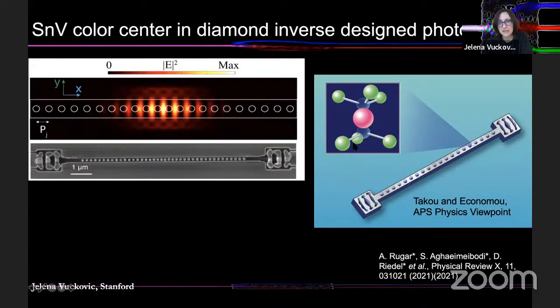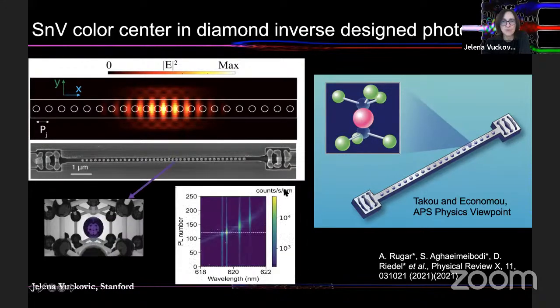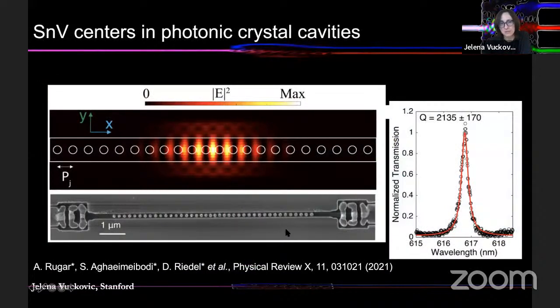Recently, we managed to do that and demonstrate a quantum photonic interface for tin vacancy in diamond, which means that we had a structure with a tin vacancy color center. We fabricated a resonator. These are also inverse design couplers. And we were able to show enhanced emission from this color center into a particular cavity mode. And very soon after this demonstration, also the Harvard group of Mark Loncar demonstrated likewise a quantum photonic interface for the same color center. So you see here how the quality of this structure looks. I mean, this was not a trivial development relative to silicon vacancy color center, because we have to operate at much shorter wavelength.